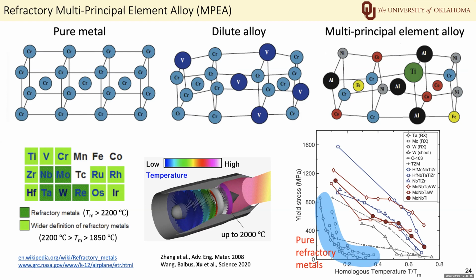At about half the melting point, their strengths are near zero. But if we mix several refractory metals to make an MPEA, there would exist a strength plateau at about half the melting point. The alloys are called refractory MPEAs, and they can retain excellent properties at high temperatures.